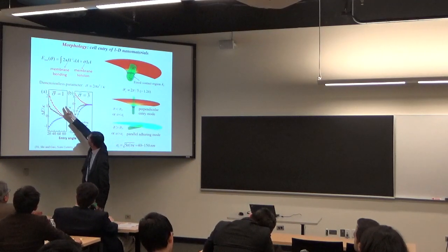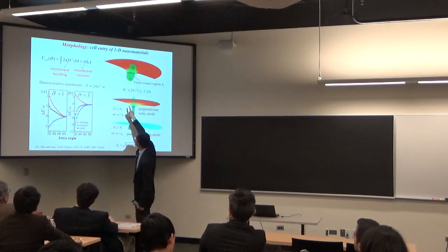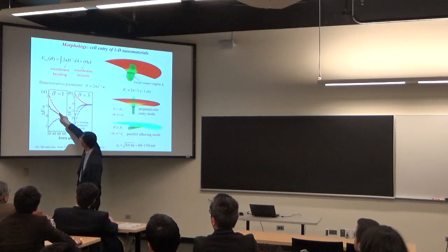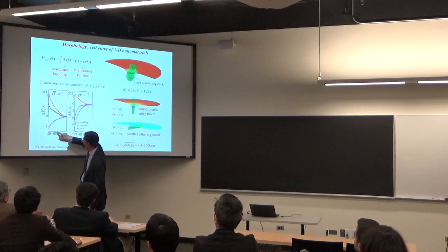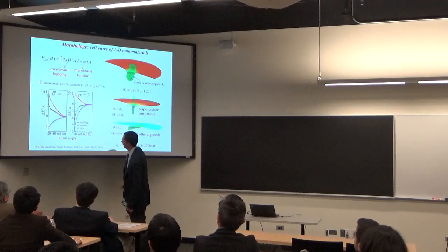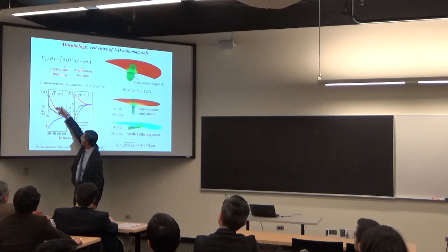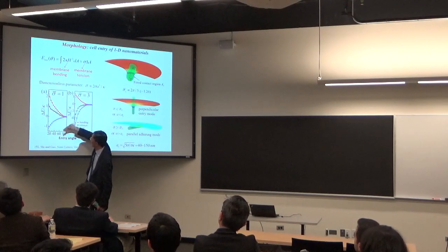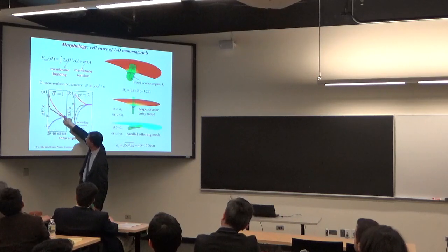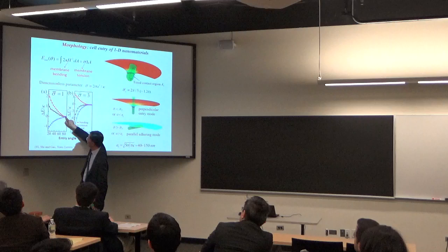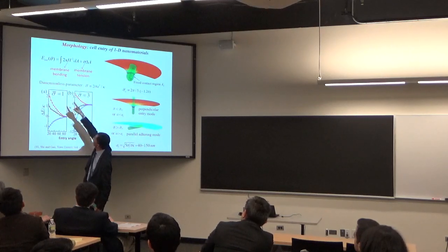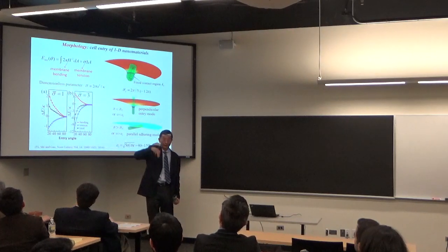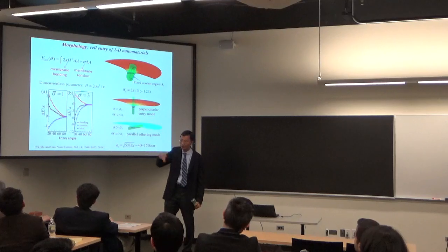Here I show you the free energy change. When sigma equals 1, that is the subcritical case, smaller than 2 pi over 5. In this case, the red curve is the bending energy as a function of the entry inclination angle theta. You can see the bending energy decreases with the angle of entry and is minimized at 90 degrees, perpendicular. The blue curve is the tension energy, which increases with the angle of entry. The black curve is the total free energy. So in this case, the free energy is minimized at 90 degrees, when the fiber is normal to the cell surface.